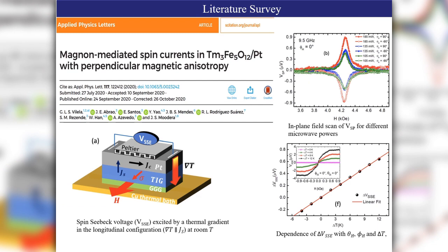So control of spin current carried by magnons in this magnetic insulator is of great interest to the spintronic field. The temperature gradient to generate the pure spin current is the key in this generation technique, which we are seeing here as the spin Seebeck effect. In magnetic insulator and normal metal bilayers, where the normal metal provides strong spin orbit coupling, the PMA benefits SOT driven magnetization switching by lowering the needed current and rendering it faster, which is crucial for developing SOT MRAMs.